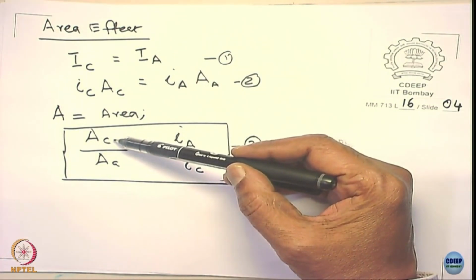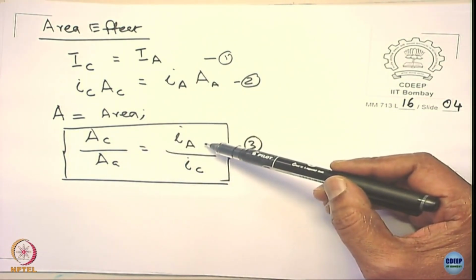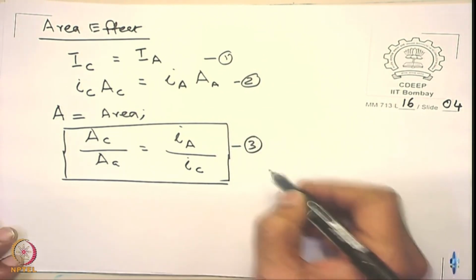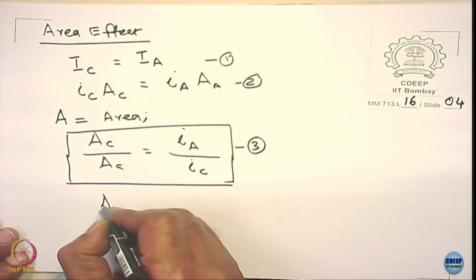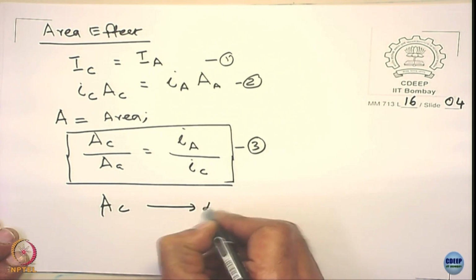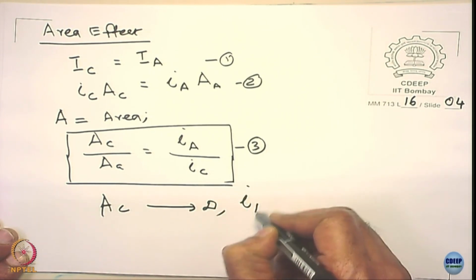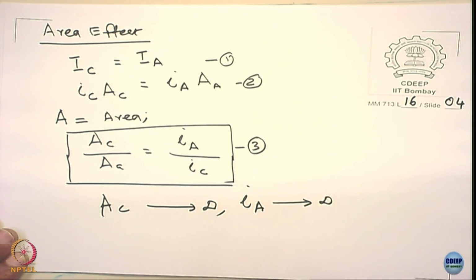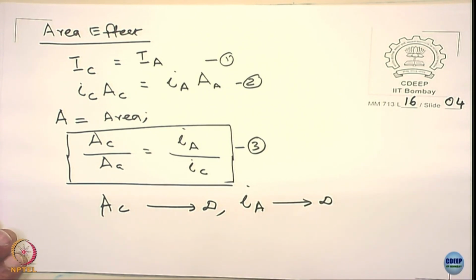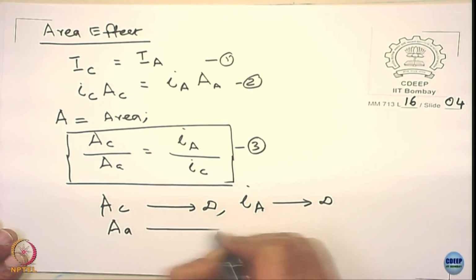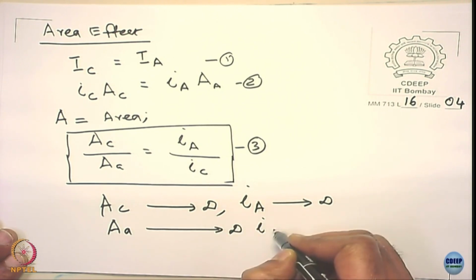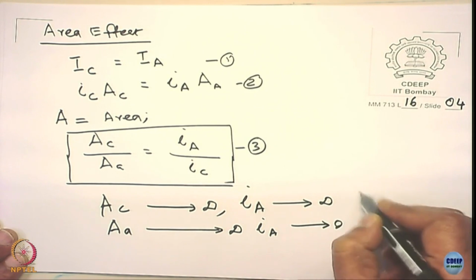If the area of the cathode becomes very high, the corrosion current density on the anode is going to be high. So, that means you can say that if the cathode area tends to become infinity, IA is going to tend to become infinity. When I say IA here, I mean the increase in the corrosion rate because of galvanic action. On the other hand, if AA tends to become infinity, IA tends to become 0 due to the galvanic couple.